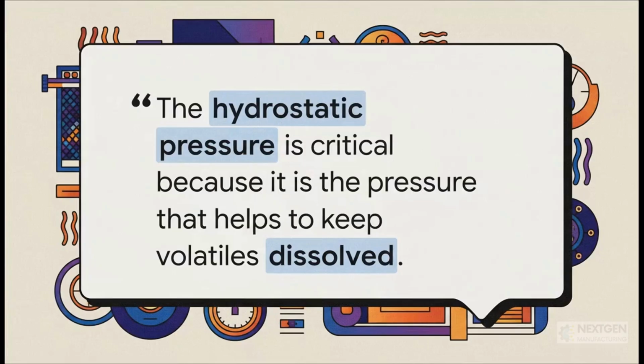This quote right here absolutely nails the key concept. It's not the 100 psi of pressure in the big autoclave chamber that matters most. It's the hydrostatic resin pressure, the actual, real pressure inside the liquid resin. That's the force that keeps gases dissolved, just like the pressure inside a can of soda keeps it from fizzing. You lose that pressure and you get bubbles. In our case, catastrophic bubbles.